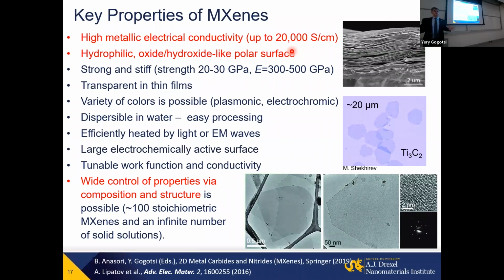And of course, it depends on the composition. Some other MXene will be less conducting. It can be up to 3-4 orders of magnitude difference. For example, niobium carbide will be just in single digits to tens of Siemens per centimeter. But you have all this range. Now, as we already discussed, they are hydrophilic. Oxide, hydroxide, polar surfaces allow this dispersion in water. And just the combination of these two properties by themselves is truly unique in the materials world.